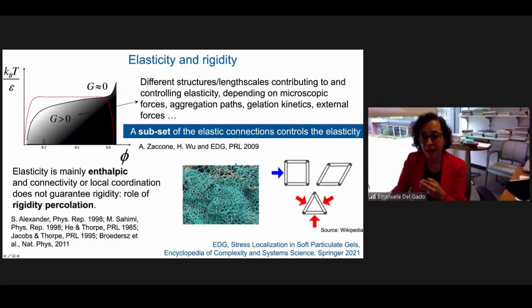So I can have a fully connected net like here, but if I don't have enough thermal fluctuations that introduce an entropic cost for changing conformation in the system, this fully connected net is not necessarily going to be also rigid. And so if my elasticity is mainly determined by enthalpic effects, then I need to have a specific organization of the structure in order to produce rigidity. Just being connected to a certain number of neighbors is not actually enough, or just to have one connected object through the system is not enough to produce rigidity.